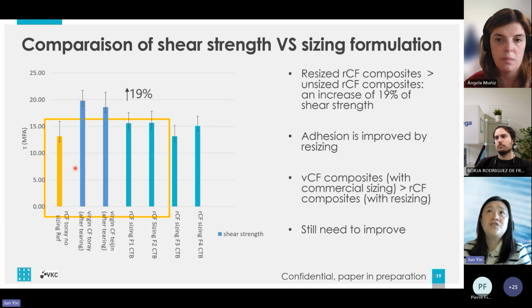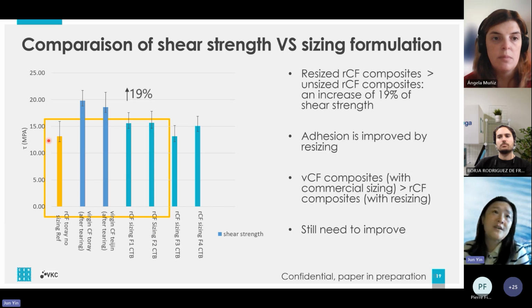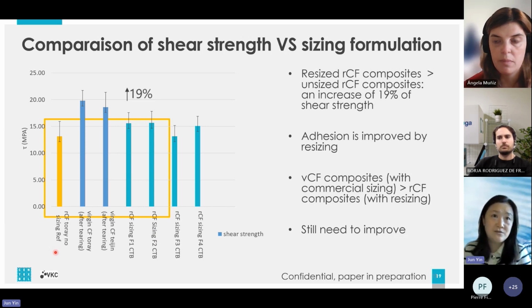We compare the shear stress of the different composites by different sizing formulations. So the first column is the composite without any sizing, just the recycled fiber. And the second and the third are the virgin carbon fibers, just after tearing the fibers, so we can consider them as virgin fiber. And the last four are the different sizing formulations. From this graphic, we can draw different conclusions.